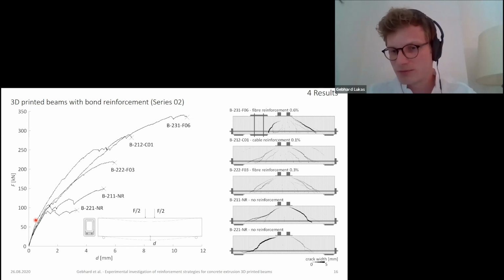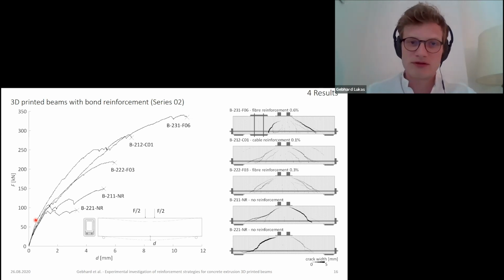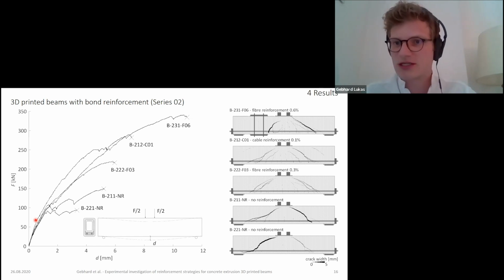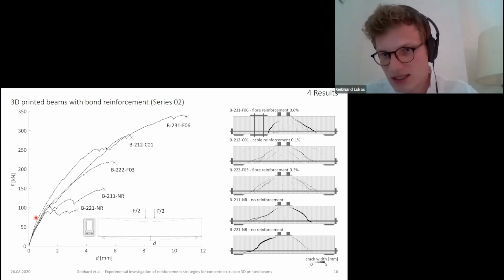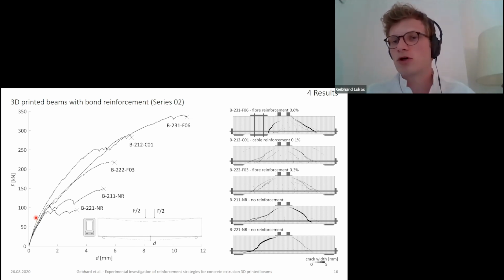All of these beams developed multiple bending cracks. However, since these cracks were significantly smaller than the shear cracks, they're a little bit hard to see in this display. For all beams where we had shear reinforcement, the load could be significantly increased. So the first increase you can see for the 0.3% of fibers with the formation of multiple diagonal shear cracks. So this time our shear reinforcement could be activated due to the bond between the conventional reinforcement and the concrete.